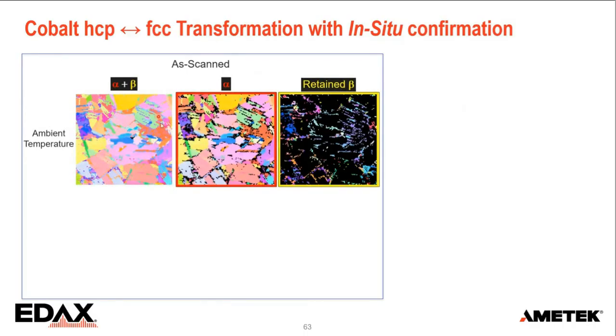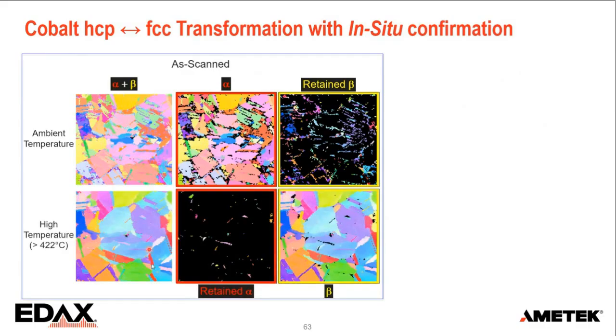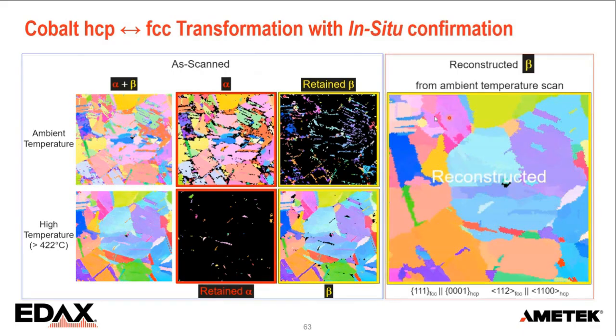Here we have room temperature, which is mostly alpha with a little bit of retained beta. When we go to high temperature, it's mostly beta with a little bit of retained alpha. So what we do for the reconstruction, we take this data set, the ambient temperature data set, and then we reconstruct that.